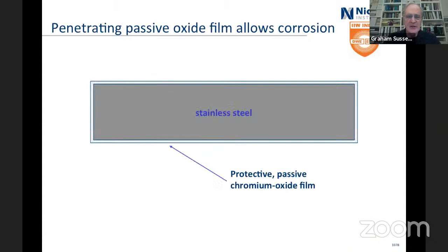So there is a piece of stainless steel. It's sitting in the middle of its chromium oxide film, and all stainless steels have that chromium oxide film. It's the basic thing. Doesn't matter whether it's duplex, austenitic or ferritic or whatever. It's this film of chromium oxide around the outside that means it's corrosion resistant. Unfortunately, this one's had a particle of steel embedded in it. And so that steel, if it gets wet, will corrode.